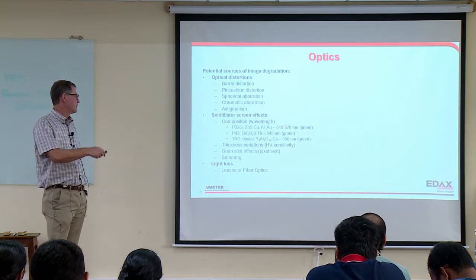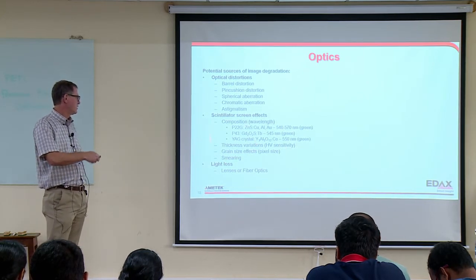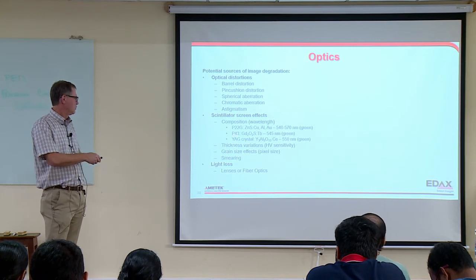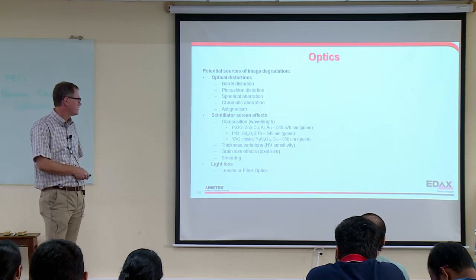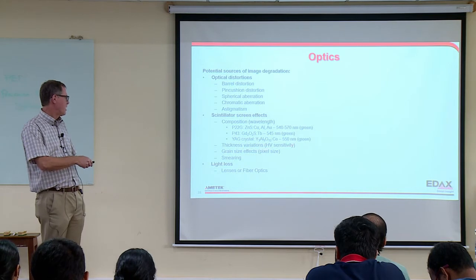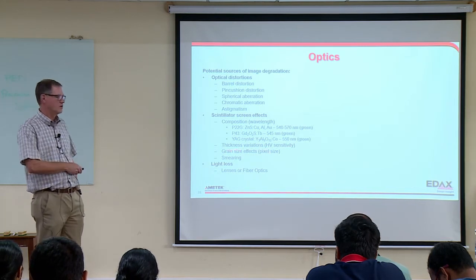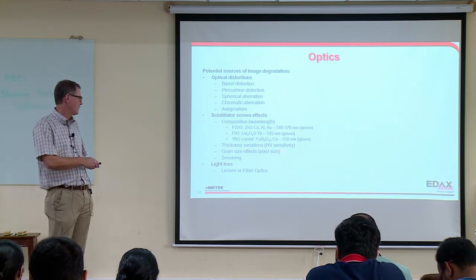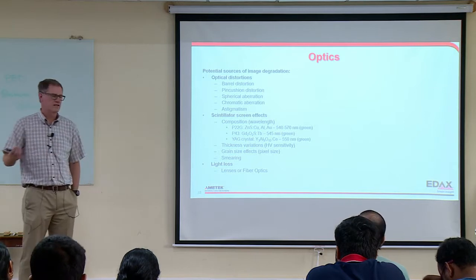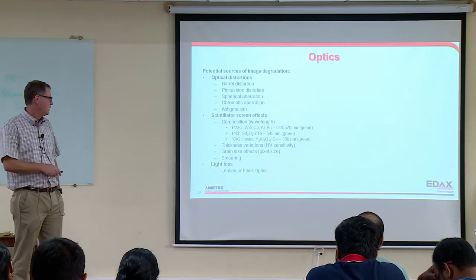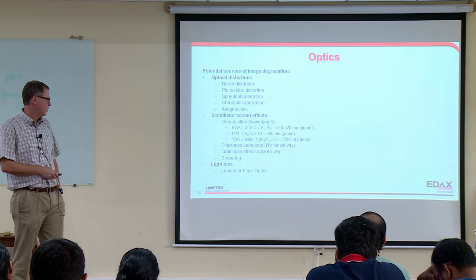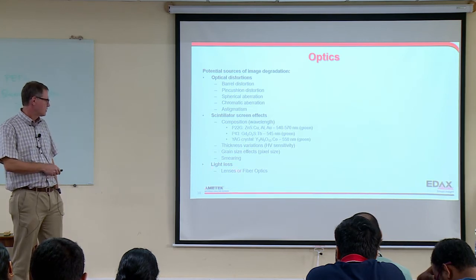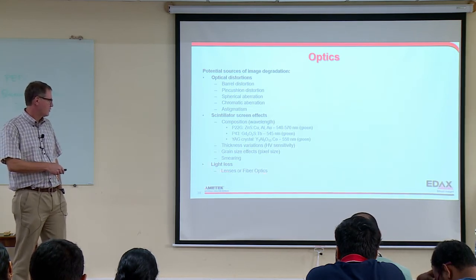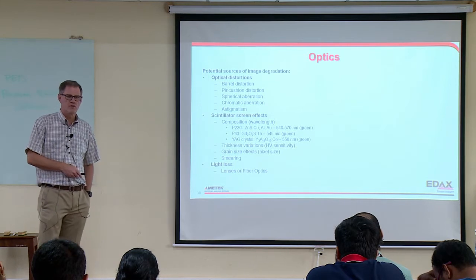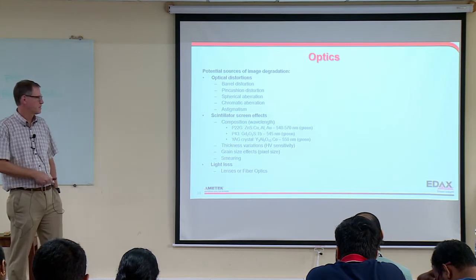You also have scintillator screen effects, depending on what kind of scintillator you're using. We've used 2 different phosphors over the years. We know they're not perfect. We have grain size effects due to the pixel size of the phosphors. We have thickness variations in the phosphor, which affects the voltage sensitivity, and phosphors produce something called smearing. We also get some light loss in the lenses, or if you use fiber optics, you also get some light loss. So as light goes through those lenses, some of it's lost.